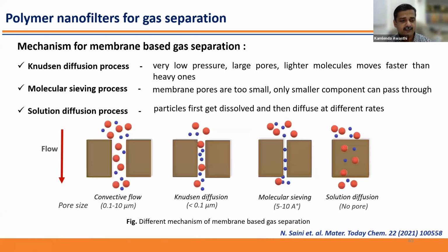Okay, this is a schematic diagram. I'm discussing it because of the porosity. Here you can see large pores, 0.1 to 10 micrometers, so every gas passes through. Here you have high permeability, but of course low selectivity. Here the porosity is slightly less, so only one kind of gas can pass comfortably and the other can be blocked. And here is molecular sieving, with very small pore distribution, so only this blue part comes out. And this is solution diffusion, in the case of a dense or composite membrane. There is no pore, but the gas is absorbed at the high pressure side and then dissolves out from the lower pressure side because of the pressure gradient.